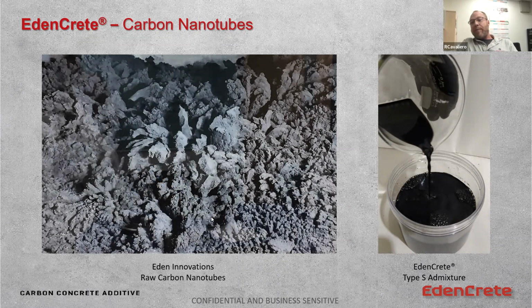We're vertically integrated. We make a proprietary catalyst that we can make to make carbon nanofibers, carbon nanotubes, carbon black, whatever we want. We make that catalyst, we put it into our reactor. We use the process of pyrolysis with methane. We capture the carbon, we flare the hydrogen, and then we take those tiny nanoparticles and we process them into this black liquid here you see on the right that is named EdenCrete.